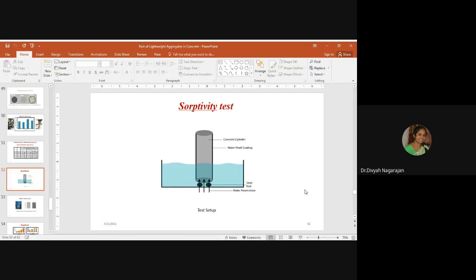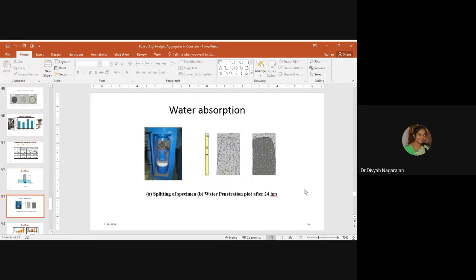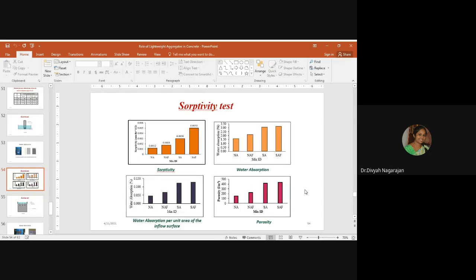This sorptivity is a property of a porous material that tends to transmit water by capillary absorption. After 24 hours of water absorption, the cylinder was split into two halves, and the water penetration plot was taken in order to know how much water was absorbed within 24 hours. The pattern of absorption of water within 24 hours was observed. The cumulative water absorption with respect to elapsed time is calculated. The rate of increase in sorptivity was observed in the initial stages. Sorptivity, water absorption per unit area of the inflow surface, and porosity were calculated from the sorptivity test.